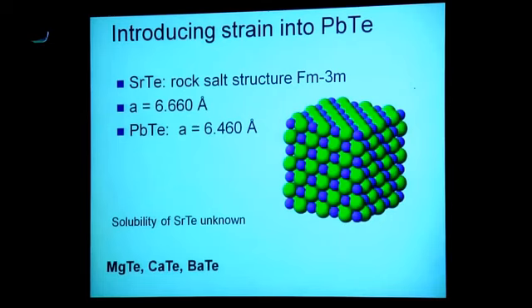So having done that, we wanted to see what happens then with other nanostructures. Especially we wanted to go on the P-type because, as I told you, the electronic structure is more favorable. It has two valence bands. So we chose strontium telluride, and this is the lattice parameter. So it has a little bit of difference here. And we also used other ones, magnesium, calcium, and barium telluride.